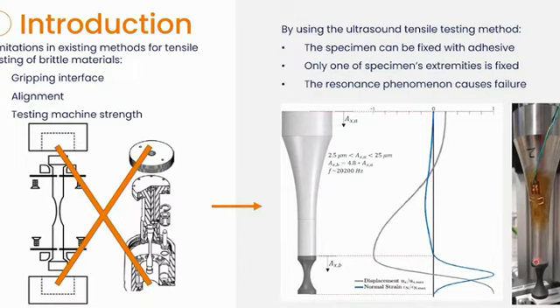And only one of the specimen's extremities is fixed, so there are no alignment problems. And finally, the resonance phenomenon is what causes the normal strain that will bring the specimen to rupture, which limits less the maximum section of material that can be used.